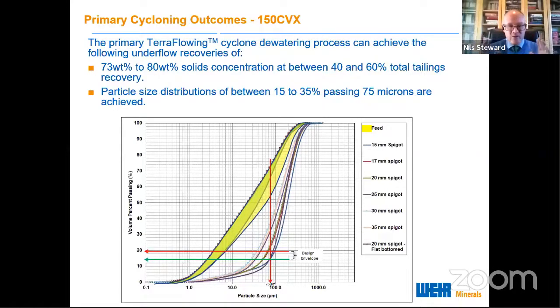I need to state quite clearly that these cyclones are not operated in the manner that you traditionally operate cyclones, as you'll see as we go through. With our primary cycloning, we're able to achieve an underflow solids concentration from the cyclone of between 73 and 80 weight percent, depending on the particle size distribution we're trying to achieve. And we get between 40 and 60% recovery of the total tailings in the underflow. Depending on what we're trying to achieve, we can get particle size distributions anywhere from 15 to 35% passing 75